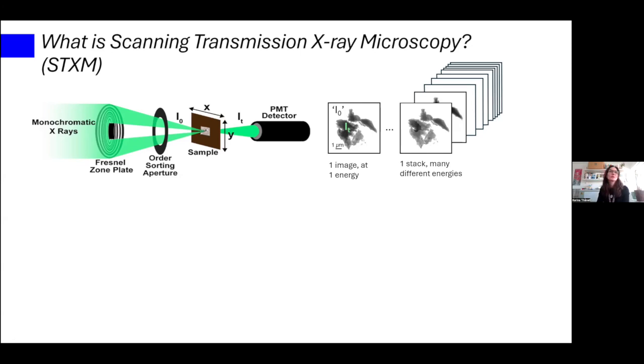What you do, namely, is take an edge of an element that you want to study. For instance, you want to look at iron in your sample. Several textbooks will tell you that around 707, 708 electron volt in the soft X-ray regime, there is an X-ray absorption edge for iron, namely the L edge. It can therefore tell you whether there is iron in the sample if you scan from below that edge to somewhere above that edge. And this is then what you can do.